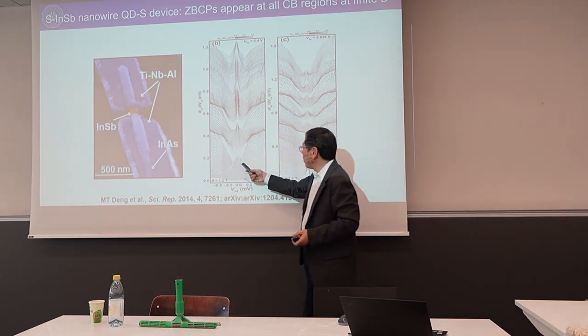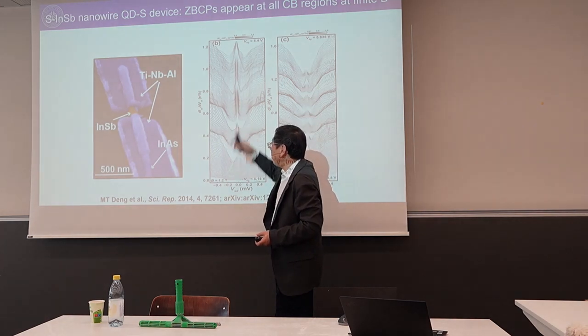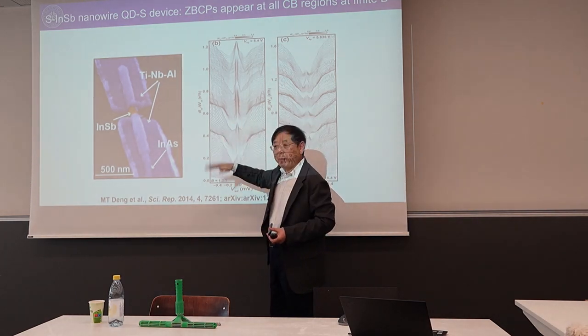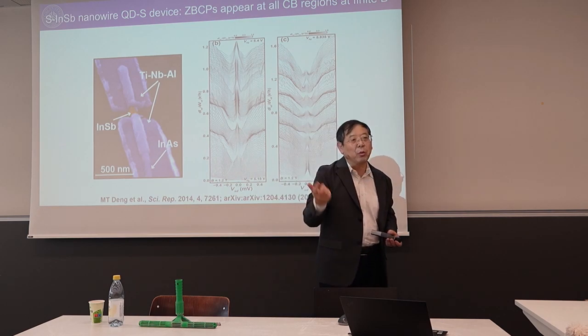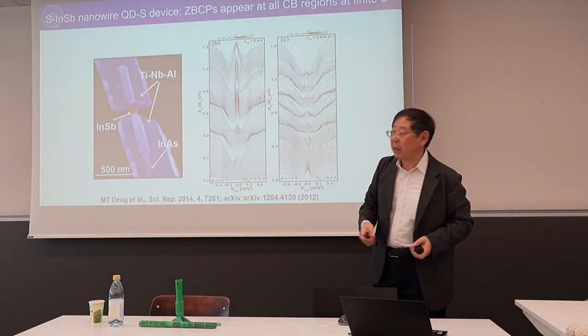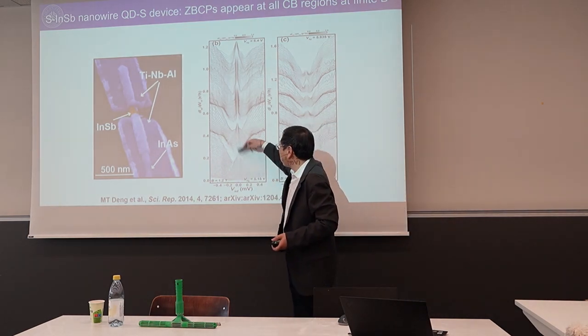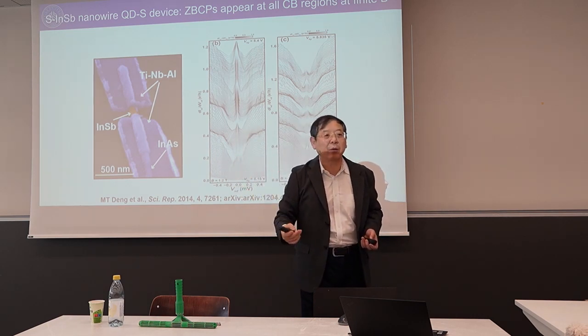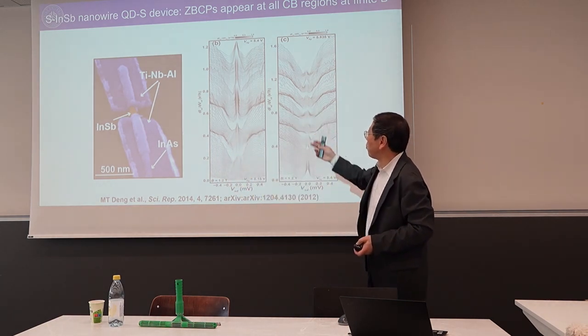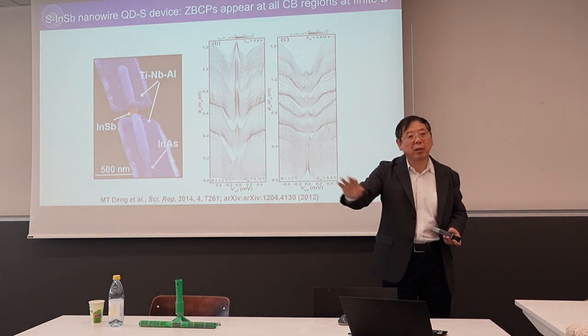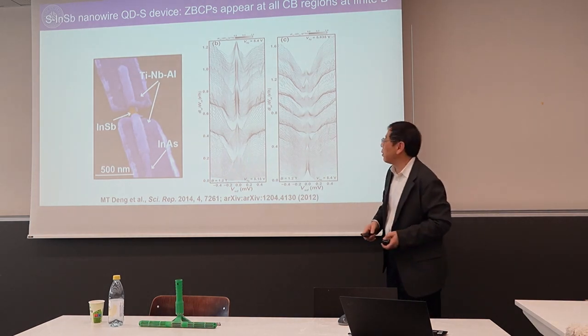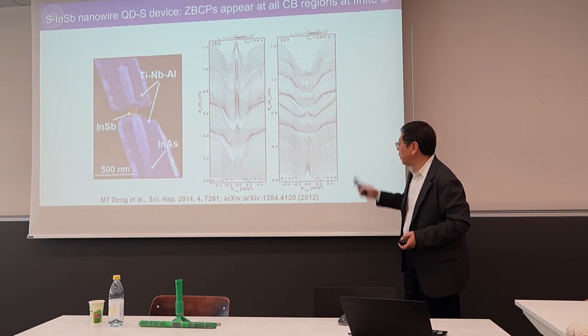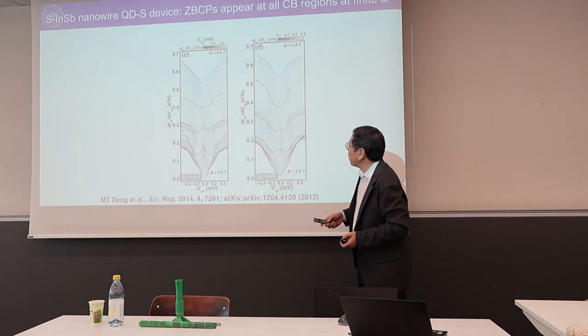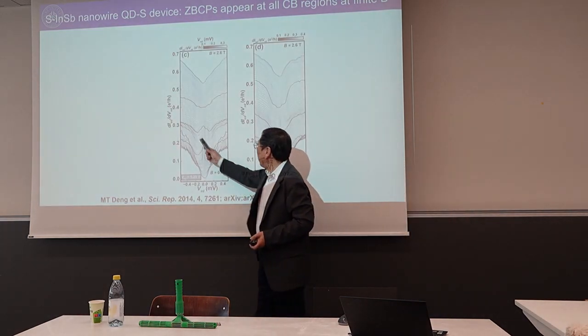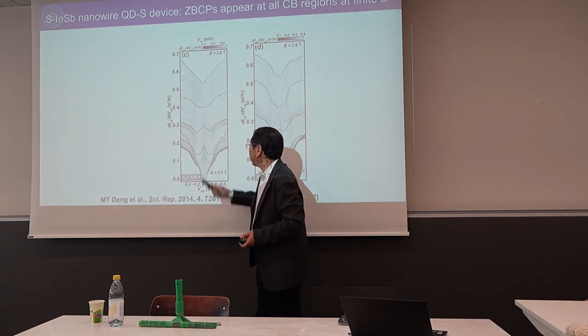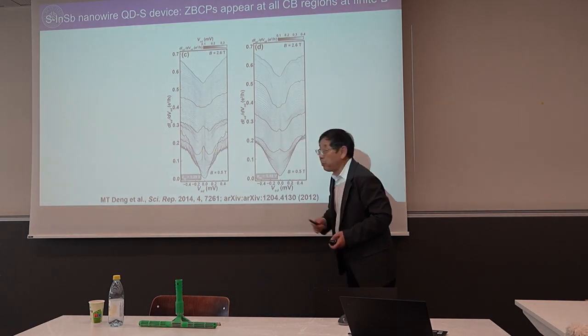The height of this peak compared to background is similar, around 0.2 e squared over h. But this is using the grid; the current grid gave the real value. So look at the oscillation, that's true. But if you subtract the background, this 0.2 height is very nice. And essentially, if you look more carefully, they are more like a triple peak structure. So they all show a triple peak structure.